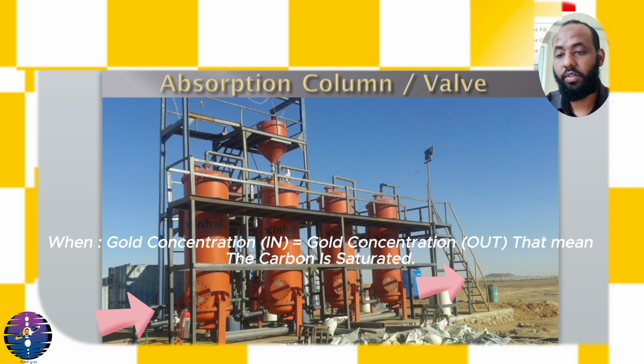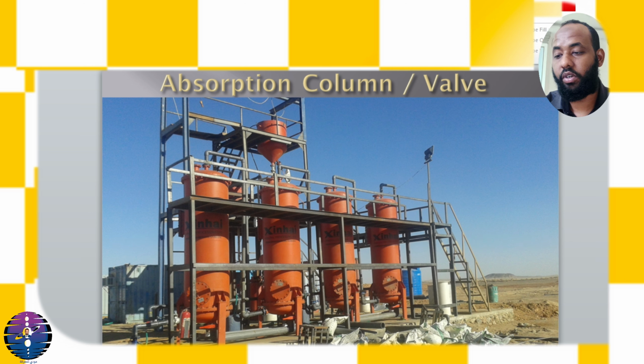When the gold concentration readings from the pregnant pond entering the absorption columns match the gold concentration readings exiting the absorption columns and flowing into the barren pond, it means the activated carbon has reached saturation and can no longer absorb more gold.